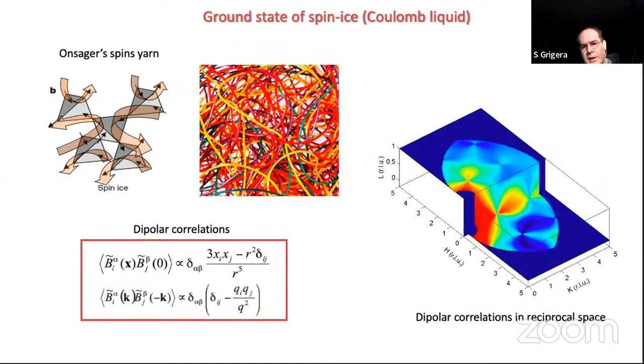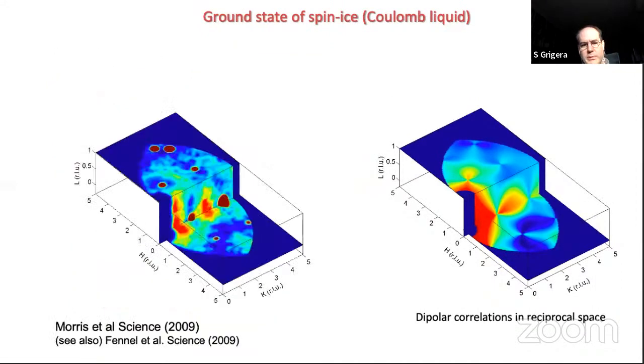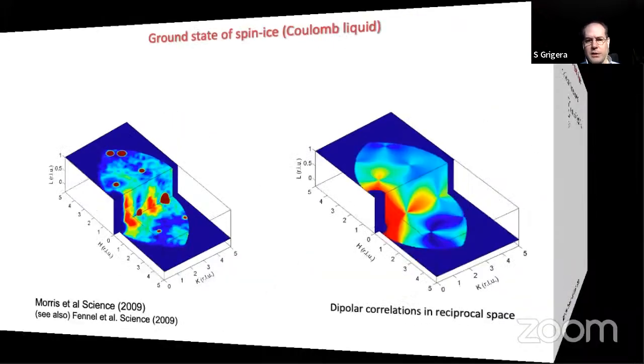So one easy way of checking whether this is true in your experimental system is, of course, you look at how these dipolar correlations will look in reciprocal space. You do neutron scattering, and you compare your measurements with what you expect to find. I would say that these measurements are not beautiful, but at least they hint that this is not a bad explanation, or it's not a bad description of the type of excitations you're seeing.